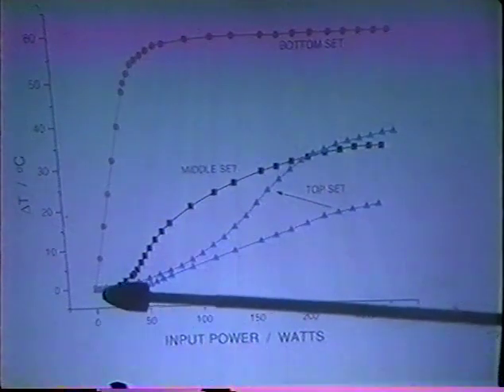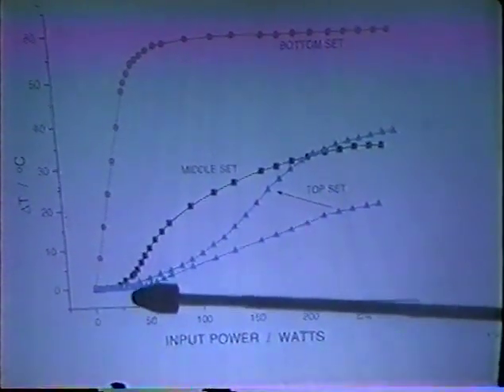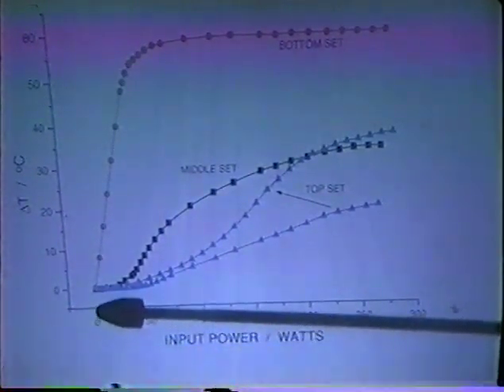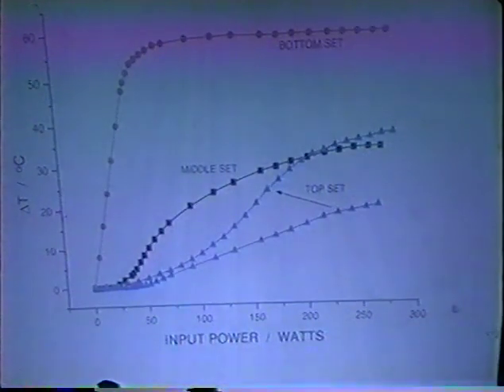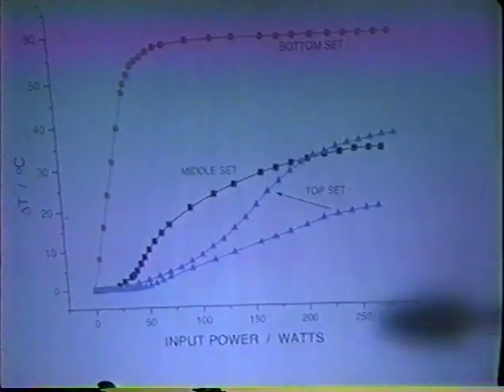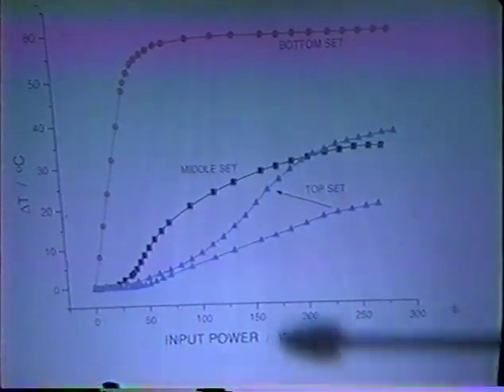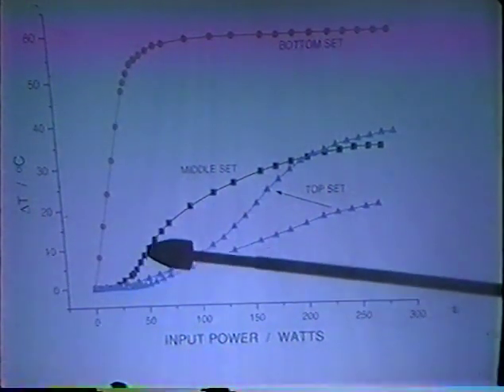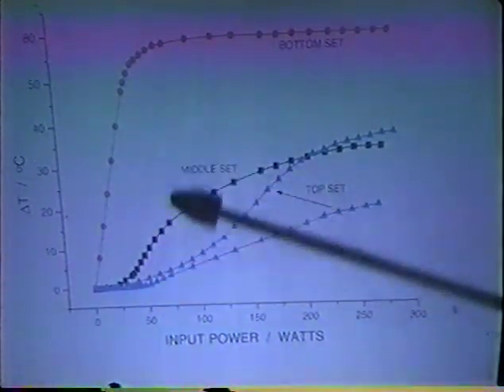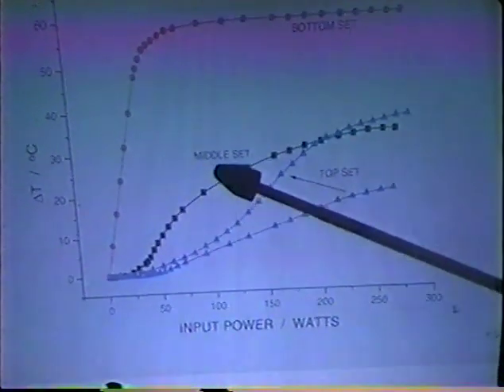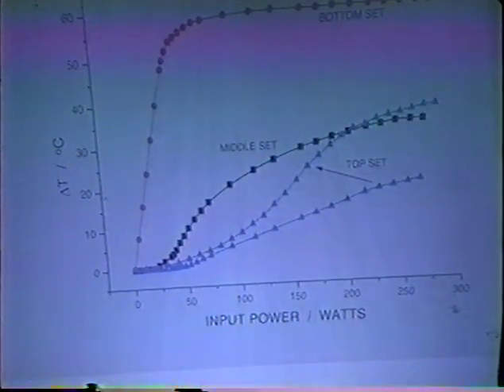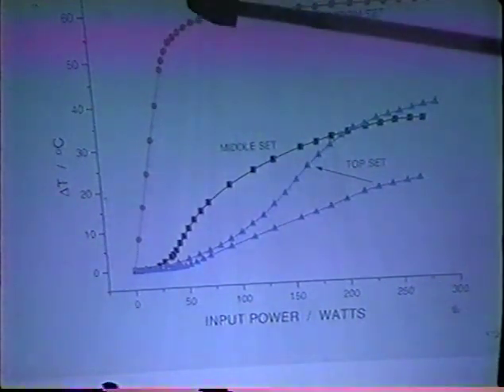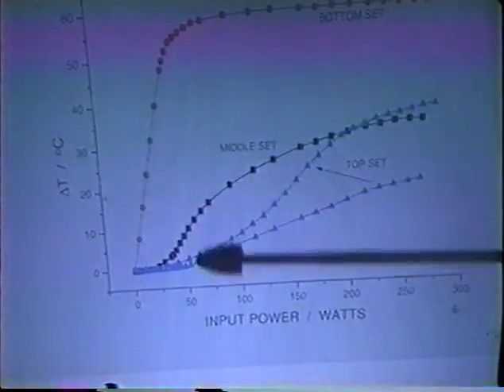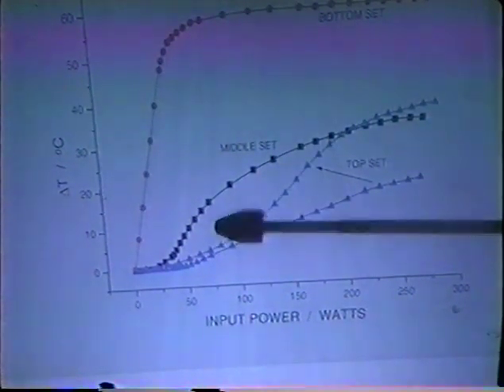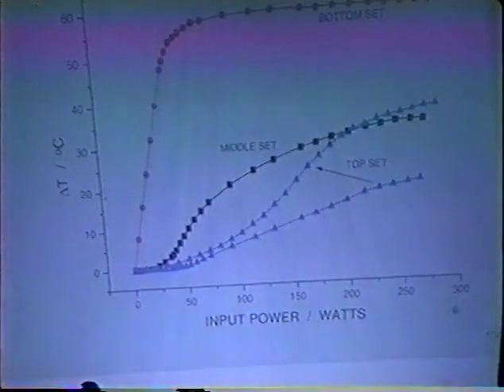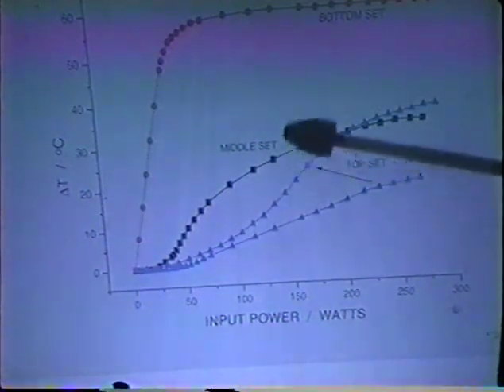A similar effect happens at the next thermistor, this middle set thermistor, that is the black curve here. It will not be so sensitive because the liquid is still quite cold and the measuring thermistors are quite far away from the hot liquid below, from the vapor. However, at some point, as the vapor starts rising in the calorimeter, you will start to measure an increase. You will have its maximum sensitivity in this region, and then the sensitivity will start to slow down, of course, as you come to equilibrium at the boiling point. The curve is delayed somewhat, of course, because the rate of rise of the vapor is then dependent on the power input, not on the temperature at the bottom of the power input.